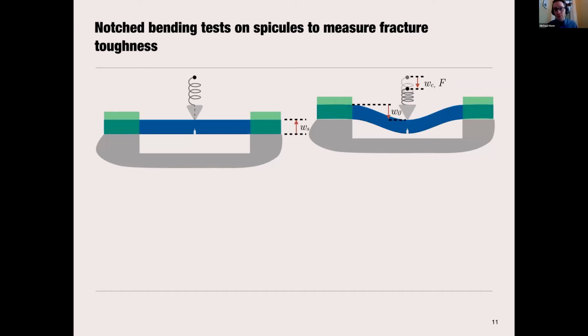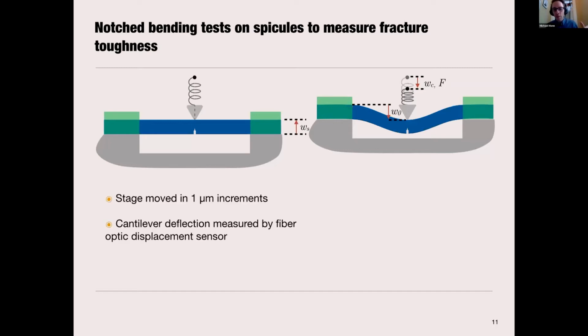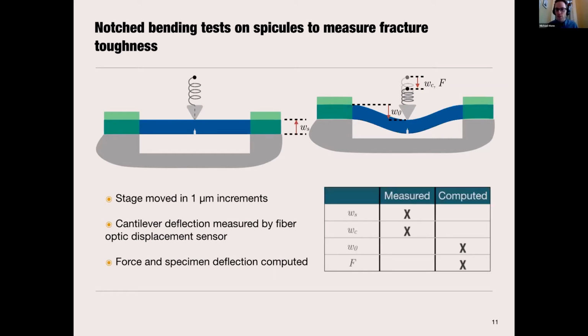And this serves two purposes for us, one of which I'll discuss a little bit later, but one is very practical. These fibers are very, very small, several millimeters long in the sections that we've cut, and about 50 microns in diameter. So handling them can be very frustrating, and gluing them down helped a lot with that. So this stage was moved in 1 micron increments, and we measured the cantilever deflection, as I said, with a fiber optic displacement sensor. And then we computed the force and the specimen deflection W naught. So that shows our measured quantities and our computed quantities.